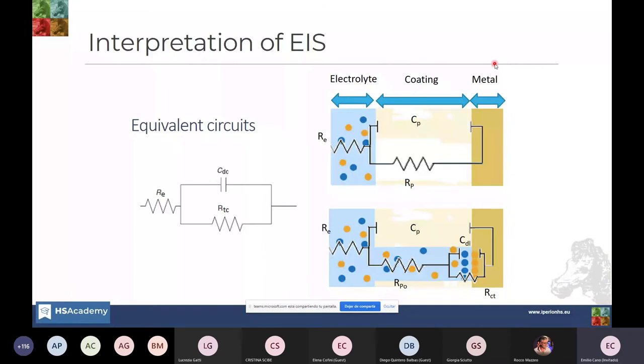When we have a coated metal, we have a slightly different system. On the right, at the top, we have a typical equivalent circuit for a good coating. Again, we have a very similar circuit, but the interpretation of these elements differs. In this case, the capacitance corresponds to the capacitance formed by the metal, the electrolyte, and the coating itself, and depends on parameters such as the thickness of the coating and the electric properties of the coating. And the resistance here corresponds to the resistance to the passing of the electrical signal through the pores of the coating.